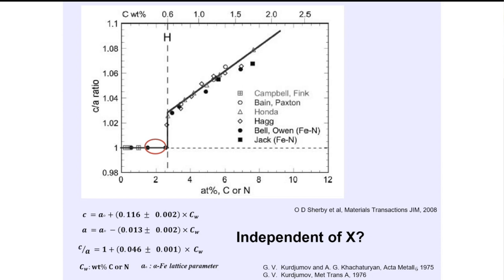The experimental data for carbon having body-centered cubic structure at room temperature exists only up to 0.2% carbon. Carbon and nitrogen both follow the same trend — the same equation of C/A ratio — even though the nitrogen atom is slightly smaller than carbon atoms. In some literature, people say this C/A ratio applies when about 80% of carbon atoms order on one of the sub-lattices, which corresponds to a Zener order parameter of about 0.7.